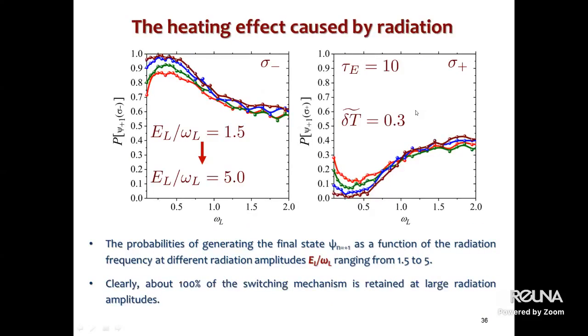So far we have neglected the heating effect caused by radiation and assumed the temperature of the ring to be constant. If we also take into account the heating effect, of course, this will influence the result. These calculations have been done for the case when the initial laser increases the temperature of the system to 1.2 critical temperatures. And we assume that the thermal conductivity may not be high enough to quickly dissipate the heat into the substrate, and therefore it may be necessary to take into account the heating effect.